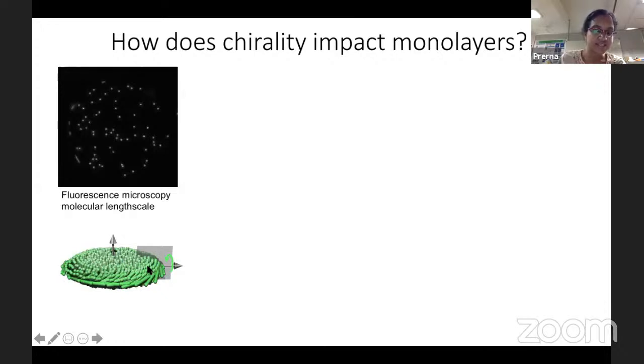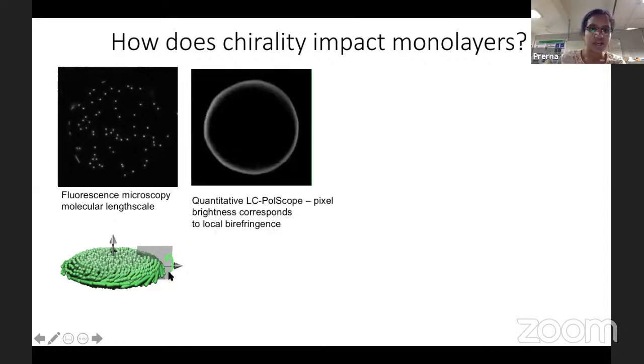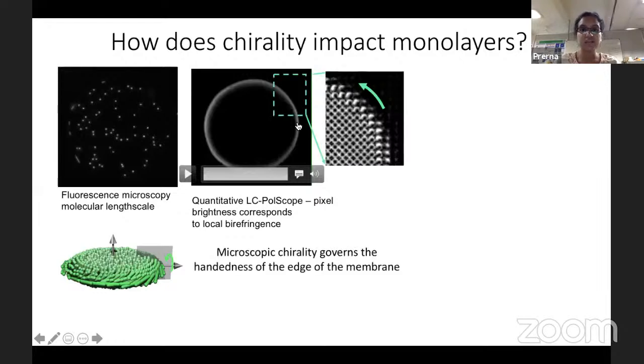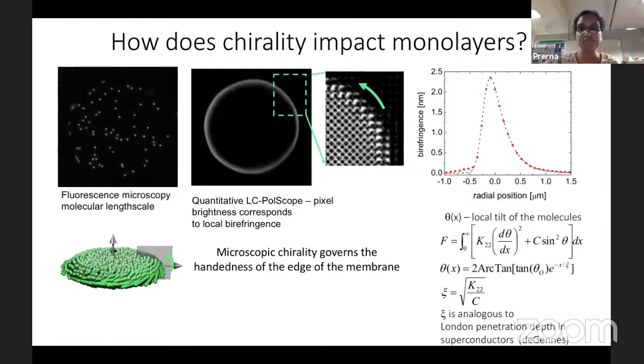So chirality, or the chiral interactions, are expelled to the edges. And you can quantify this expulsion using polarization microscopy. Here the brightness of the pixel is proportional to the local tilt of the rods. So the rods are not tilted here in the center, they're tilted at the edges. And you can do some kind of 3D conoscopic microscopy to figure out which way the rods are twisting. It's a detail that I will skip here.